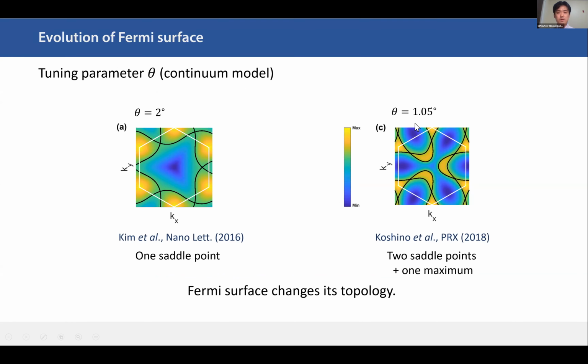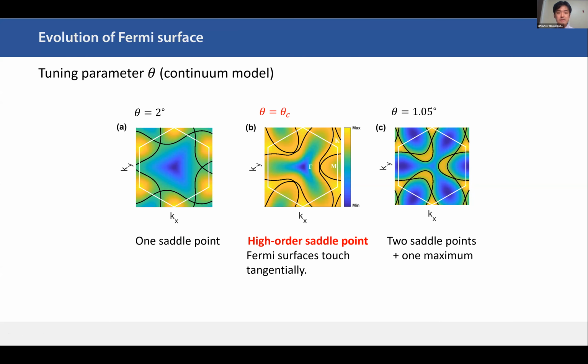And if we make the twist angle smaller, say 1.05 degrees, then the Fermi surface changes topology, where instead of one crossing here, we see two crossings of the Fermi surface and one energy maximum surrounding this small pocket here. We can clearly see the change of the Fermi surface by changing the twist angle theta. That means that there is a critical twist angle between those two different topologies. And at this critical angle, we see a tangential touch of two Fermi surfaces. We call the Fermi surface at this critical twist angle a high order saddle point.